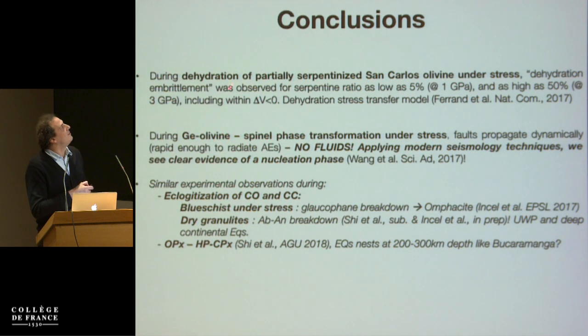So to conclude, I think I showed you that we do reproduce intermediate depth and deep focus earthquake analogs. We did some similar experiments on eclogitization of both the continental crust and the oceanic crust, and we again see acoustic emissions triggered in one case by the glaucophane breakdown into omphacite, or in dry granulite by the plagioclase breakdown. And there are some very new results where people have been looking at the enstatite to high-pressure clinopyroxene phase transformation, which also has a positive Clapeyron slope and is exothermic. This should happen around 200 to 300 kilometer depths, and that transformation could very well explain some of those weird earthquake nests that are found in some places on Earth at 200 to 300 kilometer depths.